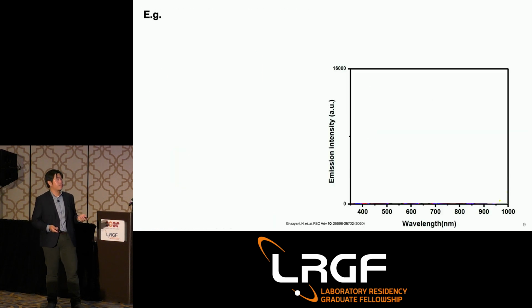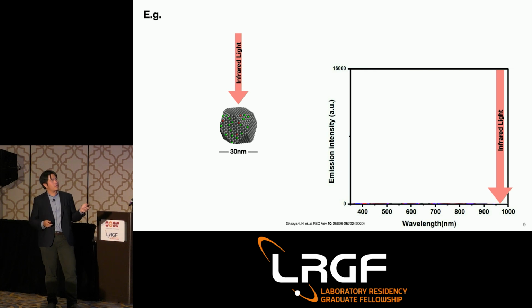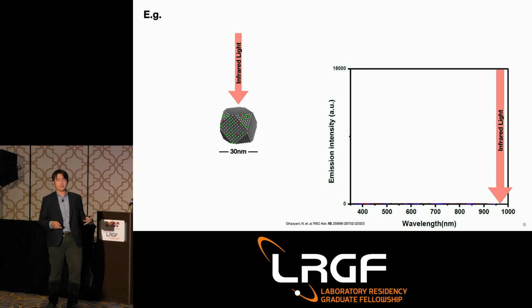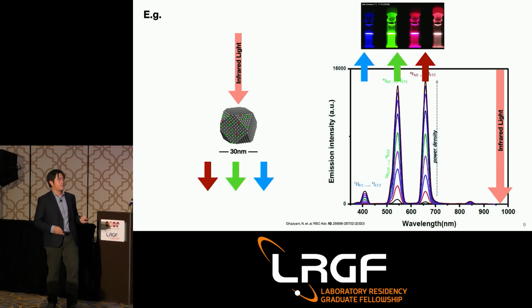potentially sensors. Now, just to harp on this a little bit more, again, you have a nanoparticle, you hit it with infrared light, but it doesn't just emit back out infrared light. Instead, it upconverts to visible emission in the blue, green, and red, typical of your ytterbium and erbium doped nanoparticles.